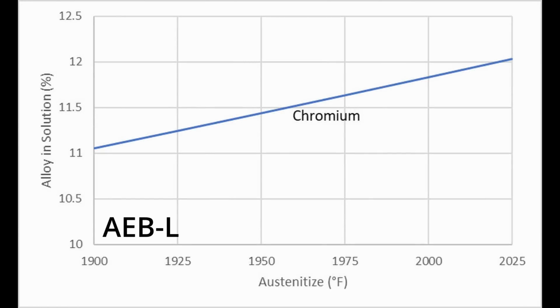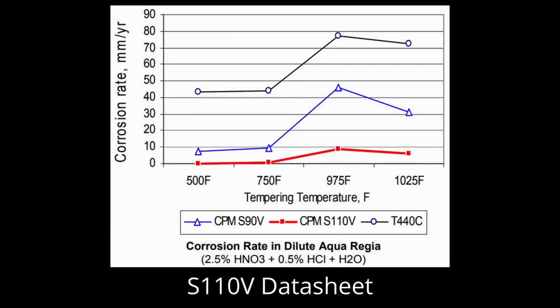Now, other heat treating variables matter apart from the quench speed. A higher austenitizing temperature means more chromium carbide is dissolved, putting more chromium in solution. And it is relatively common in industry to use the high tempering temperature range, which I've mentioned a couple times before in this video, but not too much. That high temperature range is like 950 to 1050 Fahrenheit, 510 to 565 Celsius, and that high temperature tempering range reduces corrosion resistance.